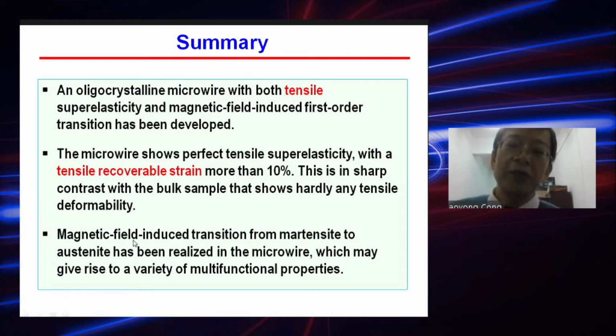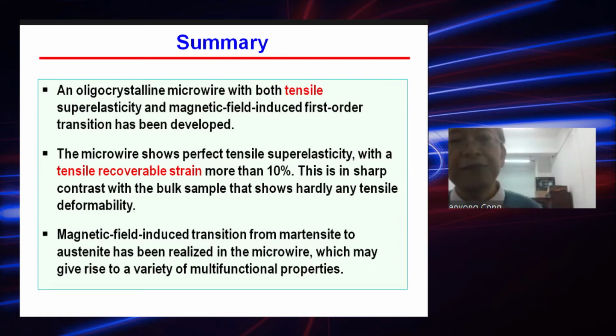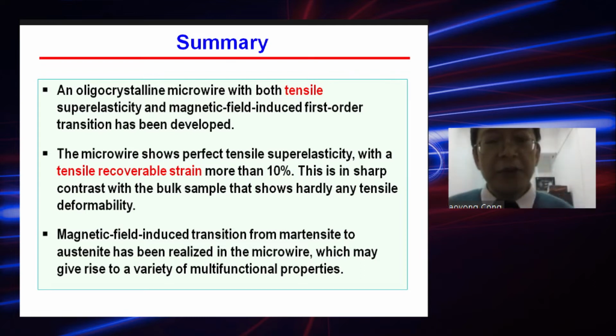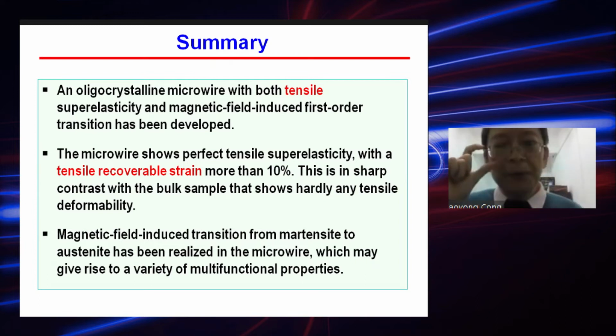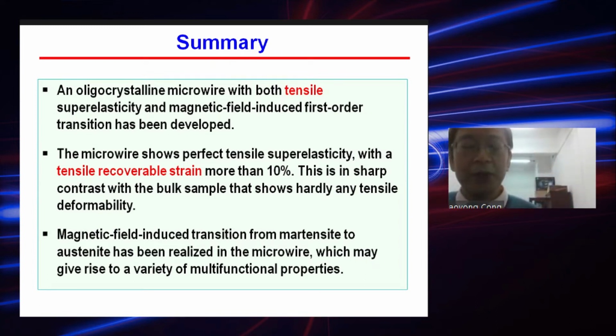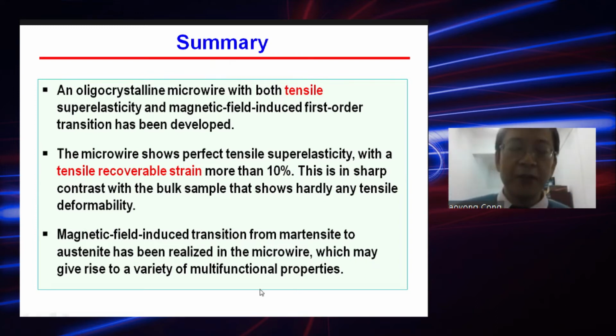A magnetic field-induced transition from martensite to austenite has been realized in the microwire, which may give rise to a variety of multifunctional properties. With stress-induced transformation and magnetic field-induced transformation in this microwire, we can try to get the multicaloric effect under both stress and temperature.